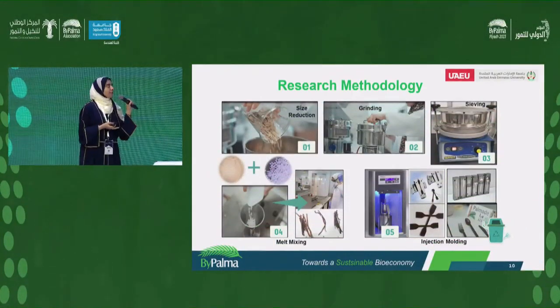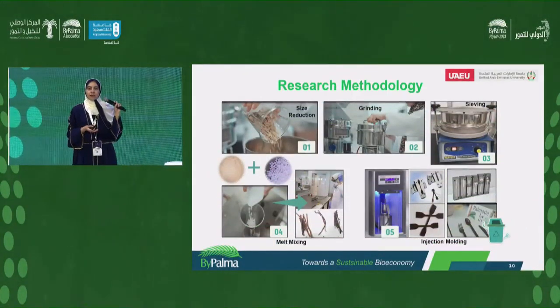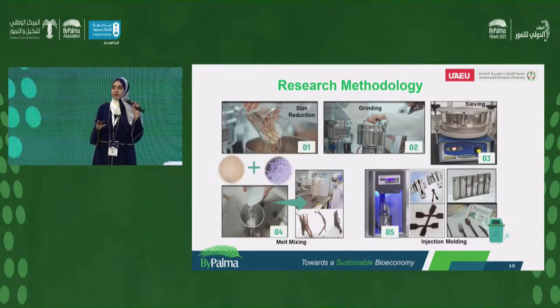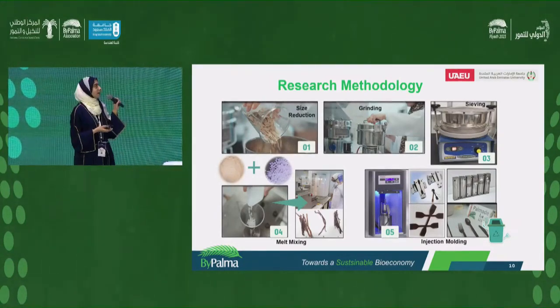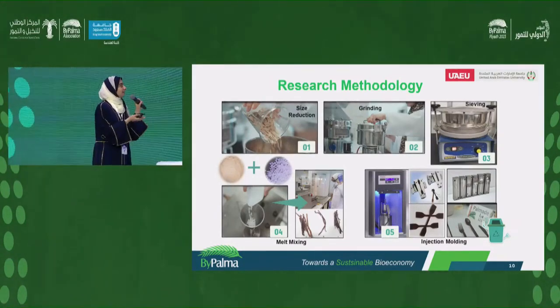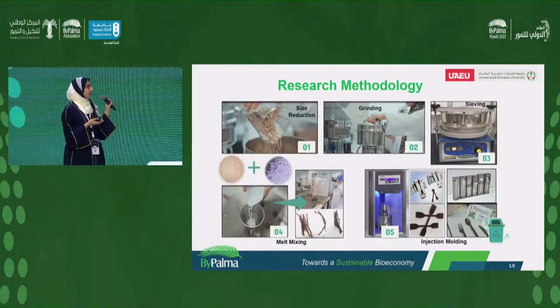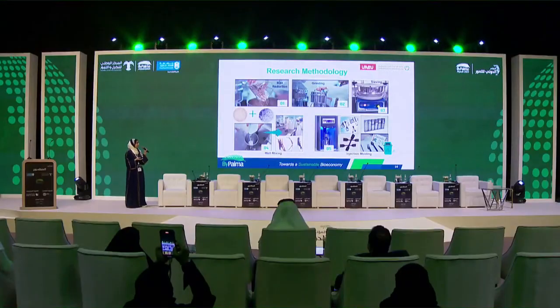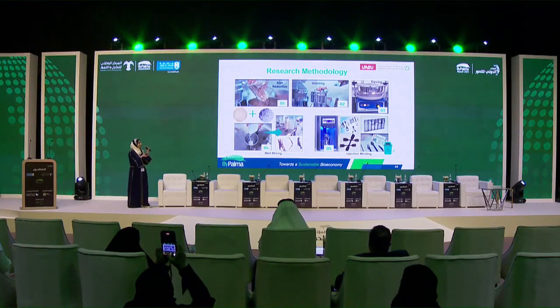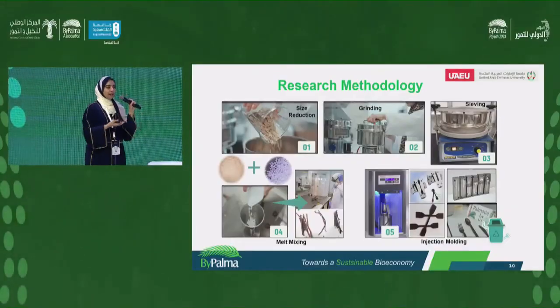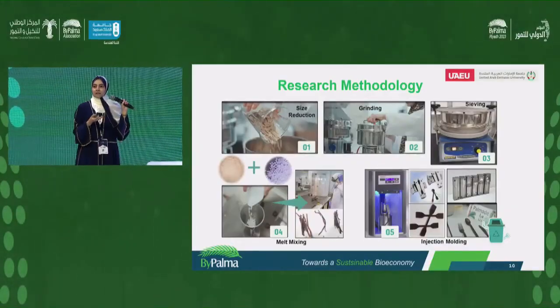The methodology started with the size reduction of the date palm waste. We used the waste from the fronds, from the rachis, and then we ground it and sieved it. Then melt mixing using an extruder for the polylactic acid and the date palm waste, and we also add the additives. And we have the injection molding for the tensile testing and to create our biodegradable cutleries using the specific needed mold.